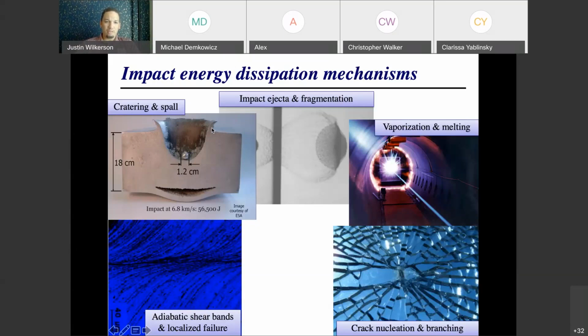There's very, very little melting that has occurred in this impact. I would say far less than 1% of the material melted in this situation. And so all of this is just due to the very, very high deviatoric stresses that are created from this impact that cause the solid material to flow like a liquid, even though it's still in its solid state. So it's plastically flowing, and it's creating that crater formation.